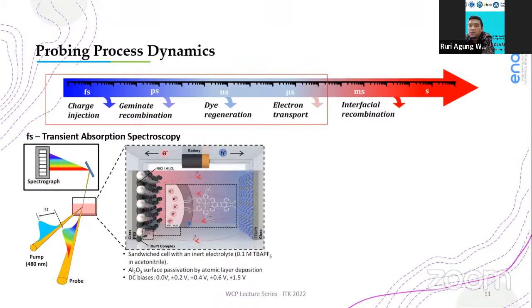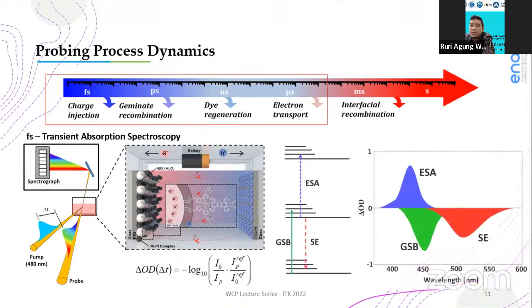As an example, transient absorption signals can be distinguished as ground state bleach, excited state absorption, and also stimulated emissions. The ground state bleach is indicated by negative delta OD, or the delta optical density, due to the loss of the ground state absorptions, while the excited state absorption is indicated by the positive delta OD, which accounts for the transitions from the excited states of the molecules to higher-lying excited states. And the stimulated emission is also indicated by the delta OD signals, which should appear at the emission wavelength of the molecules.